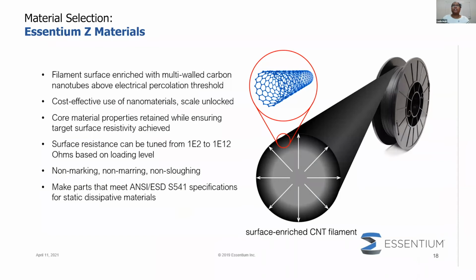With our Essentium Z line of materials, these are filaments enriched with multi-walled carbon nanotubes surrounding a core material. For example, our flexible ESD materials are surrounded by a coat of carbon nanotubes, while the core material is still TPU. So you're still getting the core material properties, or the elastomeric properties of this material, while also ensuring that your target surface resistivity is achieved. The surface resistance that we're looking for can be tuned during our production process. If you have a specific application where our material may not meet your needs, we can tune it from 1e to the 2nd to 1e to the 12th ohms based on the carbon nanotube loading level.